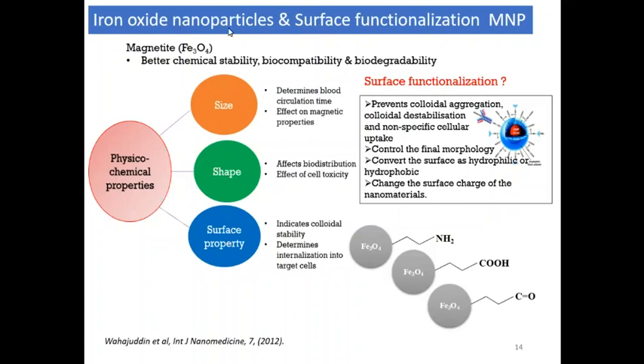So if you see the iron oxide nanoparticles and surface functionalizations, there are different functionalizations, and based on the size, shape, and surface properties, the physicochemical properties, especially the magnetic properties which we are looking at, are getting changed. There are amine functionalizations, carboxyl functionalizations, zwitterionic or positive and negative functionalization groups, and sometimes we have polymer functionalizations also.